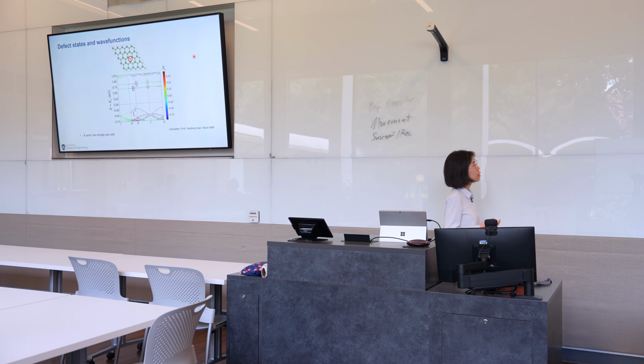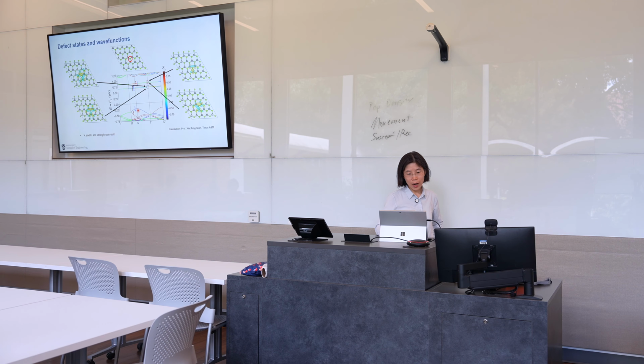So here we consider a single defect or vacancy in tungsten diselenide monolayer. You can see these K and K prime values are indeed strongly spin split. But you can also see these flat bands that correspond to the defect bands. They are actually spin degenerate. And this means they can host excited electrons with arbitrary spin.